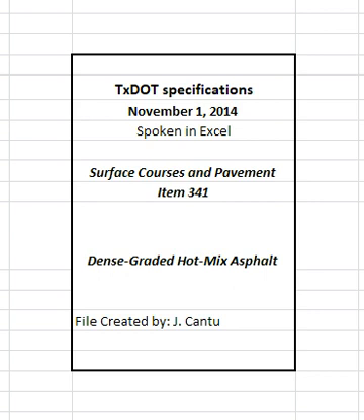2.6.2 Warm mix asphalt, WMA. Warm mix asphalt, WMA, is defined as HMA that is produced within a target temperature discharge range of 215 degrees Fahrenheit to 275 degrees Fahrenheit using approved WMA additives or processes from the department's MPL. WMA is allowed for use on all projects and is required when shown on the plans.